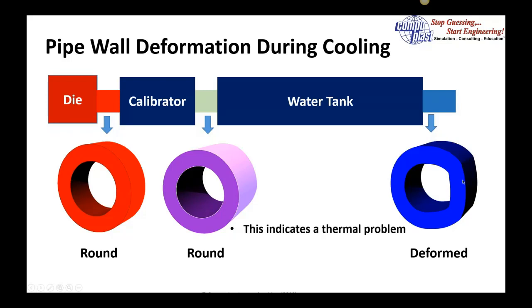This typically indicates a thermal problem, and you can easily verify it by simply slowing down the extruder and reducing the amount of shear heat the screw generates. When you slow down, you reduce the temperature almost immediately. If the problem gets reduced, then you know it's attributed to the screw design and the shear heat being generated.